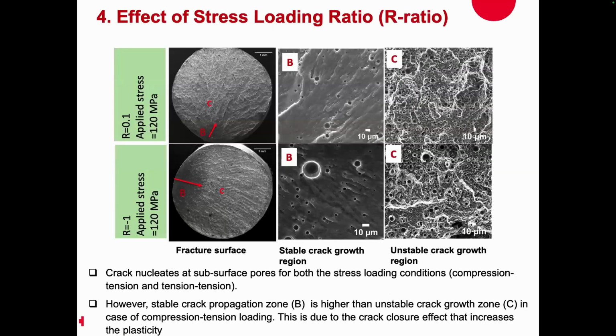This is another effect we can see. Going too deep into fracture mechanics, this is the last, I think, 1 or 2 slides. You can see for a completely reversed loading, tension compression, the fracture surface, this is tension. Look at the stable crack growth region and unstable crack growth region from the micrography. We can see the crack nucleates at subsurface pores for both stress loading conditions, which is okay.